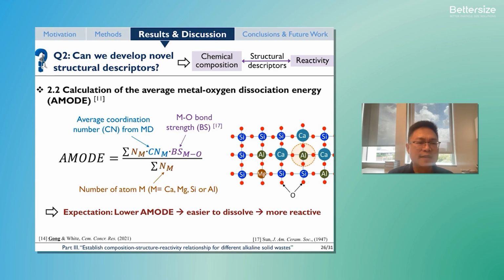So overall, this equation tells us the average energy that is required to break all the metal oxygen bonds in the material. Based on this definition, for a material with a lower AMODE value, it means that on average it takes less energy or less effort to break all the metal oxygen bonds or to dissolve the whole material to allow it to participate in reaction. And therefore, it's going to be more reactive.